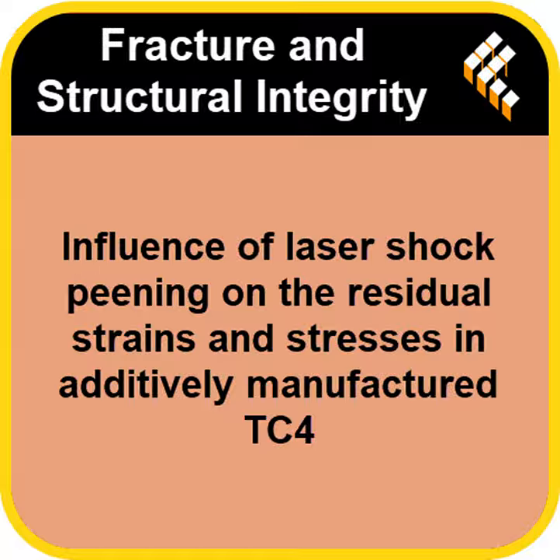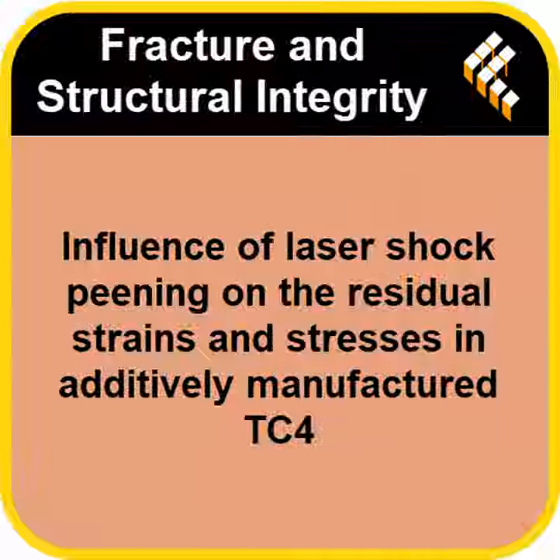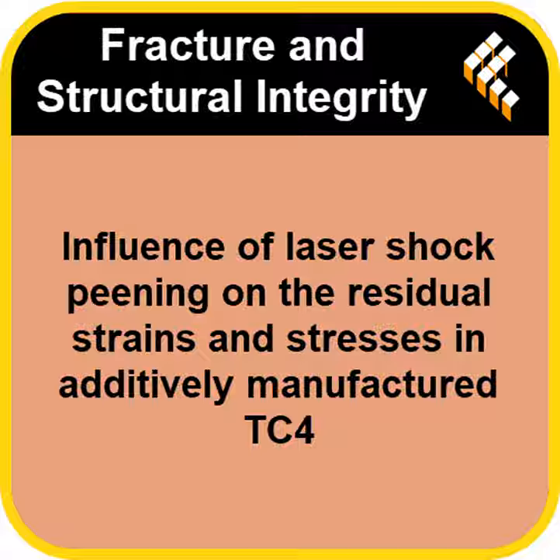And the big takeaway seems to be that how well LSP works is deeply connected to how the part was printed in the first place. That anisotropy, the build direction, it matters hugely. You absolutely have to consider the material's initial state when designing the LSP process. It's not a one-size-fits-all treatment. So it's this fascinating loop. Printing creates a flaw, LSP fixes the flaw, measurement confirms the fix, and modeling predicts the fix for future complex designs. It really closes that loop, moving towards more predictable, reliable additive manufacturing.